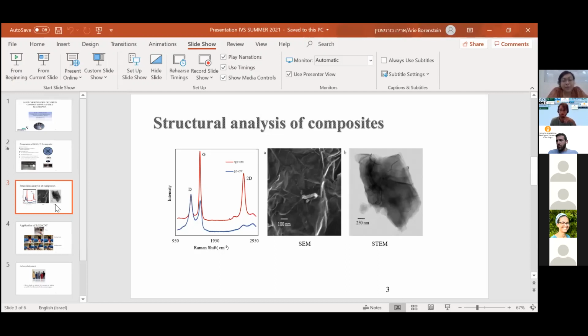So you can see in the graph that for the GO-CNT composite, the D band is larger as compared to the G band, but after the laser carbonization, for the RGO-CNT composite, the G band becomes intensely strong, and another peak, the 2D band, appears at the 2700 inverse centimeter region, which is the characteristic peak of the graphitic sp2 material. So we can confirm the conversion of the GO-CNT to RGO-CNT by this study.